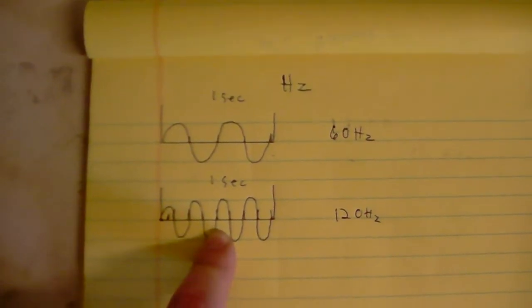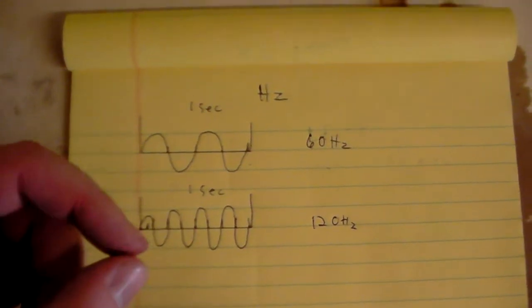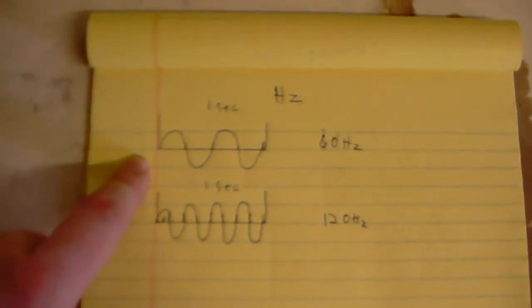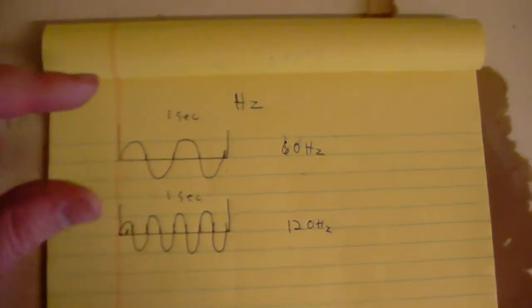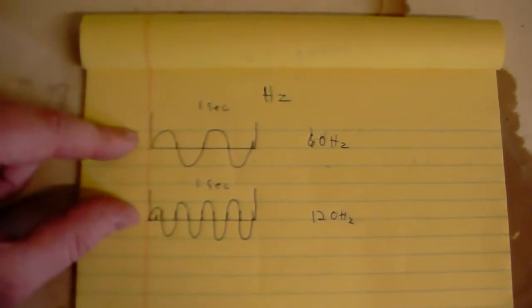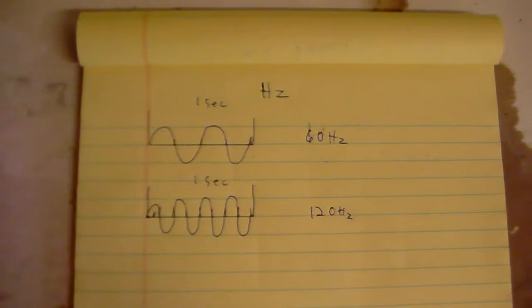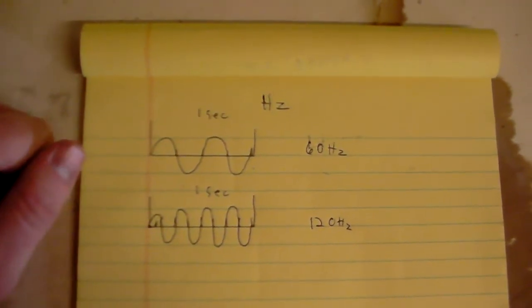So if you keep your hertz higher, you won't run into that situation where your arc keeps getting wider and wider because your tungsten keeps balling up. It'll help keep your tungsten shaped better so that you can make a more controlled and precision weld. So that's the other point with hertz. So the hertz and balance all work together, and you can do a lot of different things with your AC arc on the newer machines that can help you tackle a whole bunch of different welding applications. So let's go ahead and we'll head over to the machine, and I'll show you the settings that I'm going to use to run a bead on this plate.